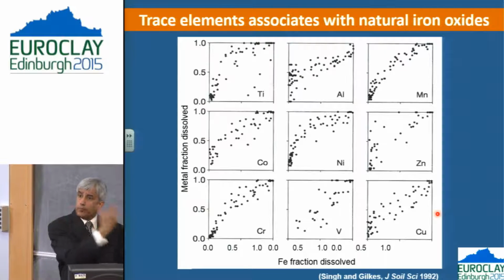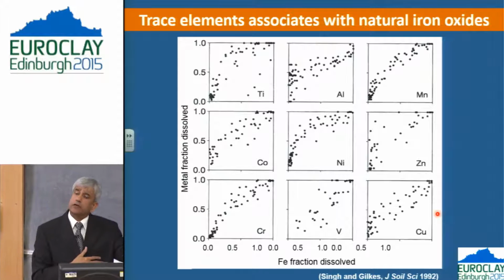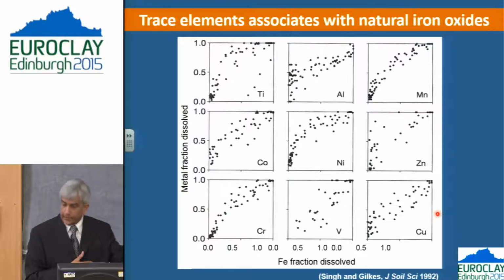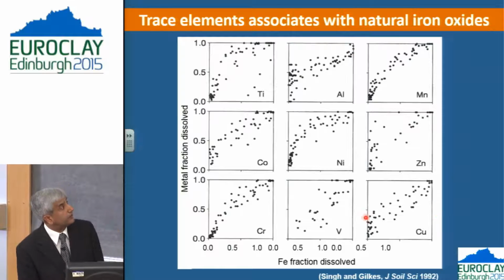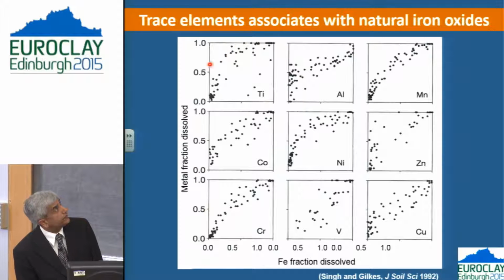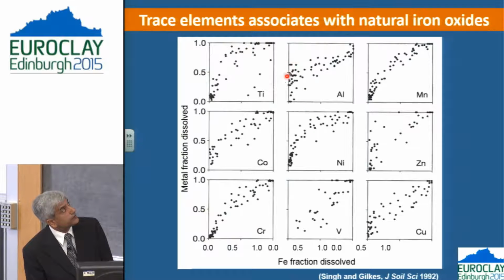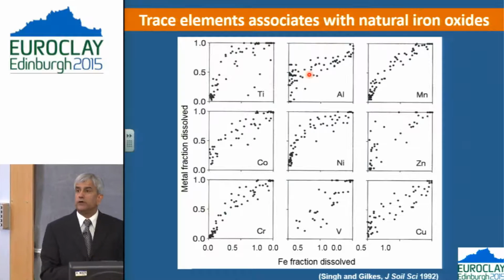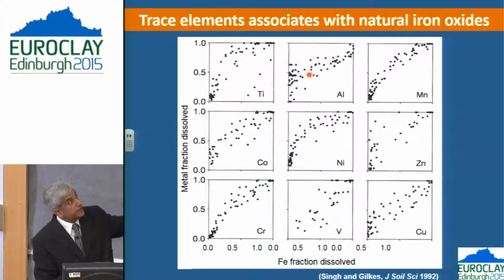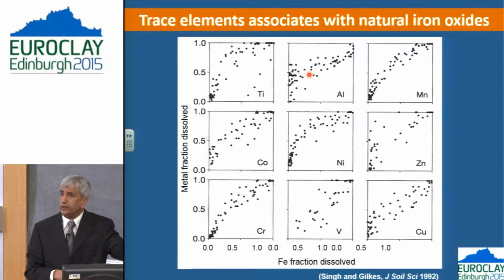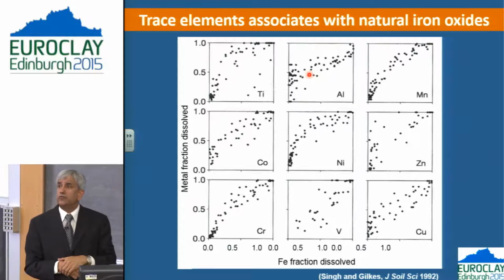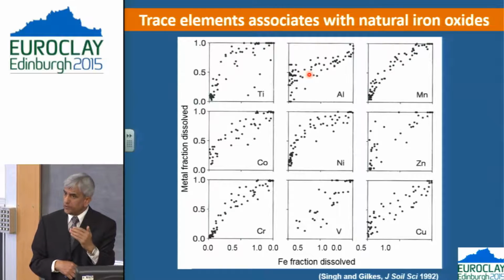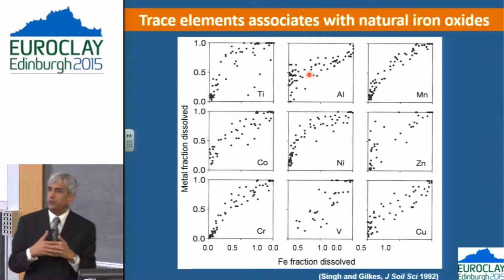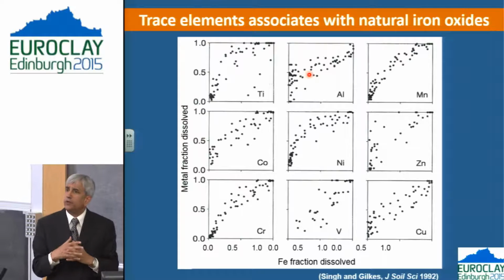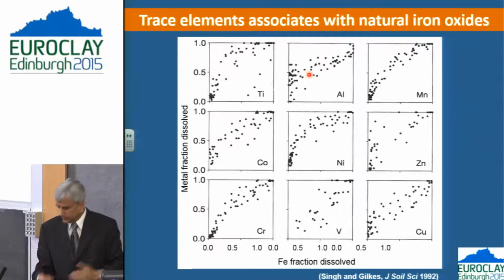So what we proposed as a result of this was that a lot of these elements are probably incorporated in the structure of iron oxide. Some of them probably are not. They are either existing as a separate phase. As you can see here, there is a lot of Mn in here as well. So that separate phase is dissolving and giving a completely different trend. But nevertheless, it shows a fairly clear trend that a lot of these elements are either adsorbed very strongly and released during acid dissolution, or they are incorporated in the structure, so they dissolve along with iron.